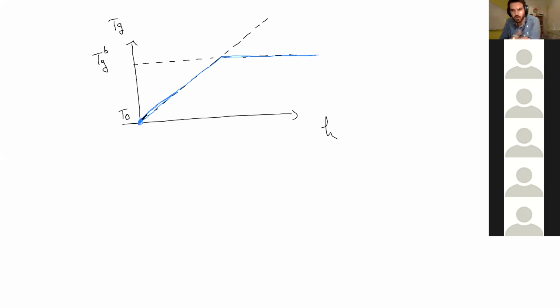And if you finish with the orders of magnitude in the tutorial, you will see that this typically occurs around 100 nanometers. So it's exactly what is observed in the experiment. There is a kind of mesoscopic length scale, which is much larger than the monomeric one, below which you start to see TG depressions. And so this model is good for that. So there are very good aspects. You see a linear behavior in H that is reminiscent of the reality.